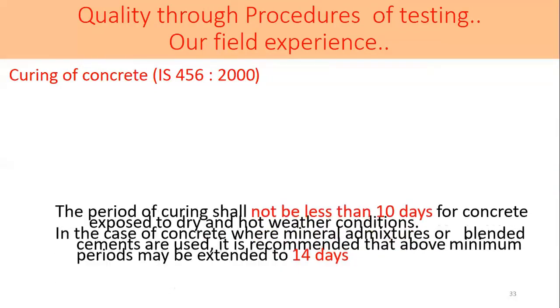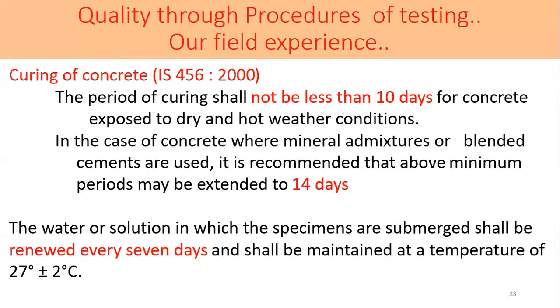Curing of concrete, next please. The curing of concrete is also an equally important thing. How are we curing that concrete? It should not be less than 10 days for ordinary concrete when it is exposed to dry and hot weather conditions. But nowadays in the field, we go for blended cements. In the case of blended cements, the minimum curing period should be 14 days. But with all the compulsions on the site and the speed which is already pre-decided, irrespective of the quality, we finish the entire curing operation within 7-8 days, and we just run after the next stage of construction. So that period is not followed.